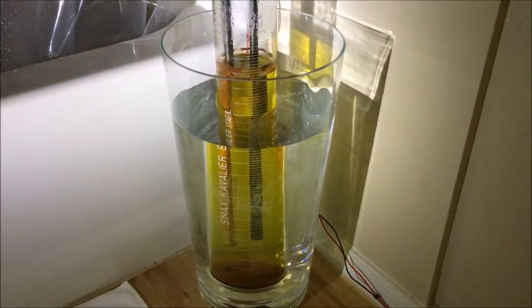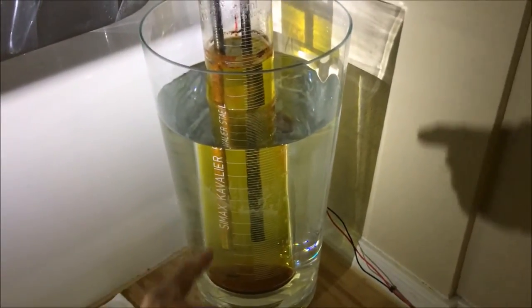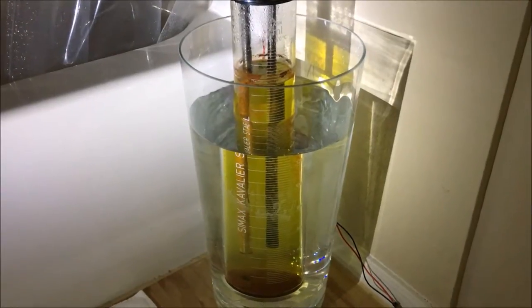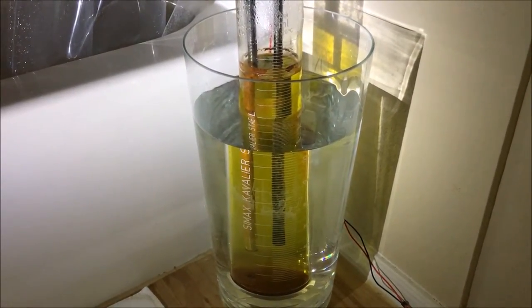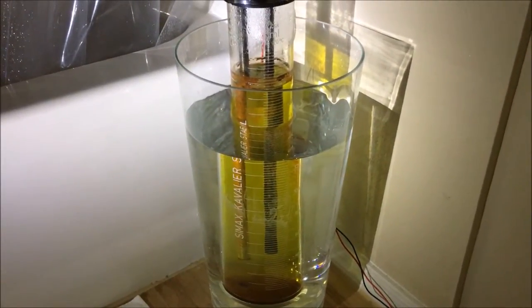However, after I left the solution over the weekend the coolant bath level went down considerably and I suspect that the system overheated and resulted in the destruction of the positive anode plate of stainless steel.